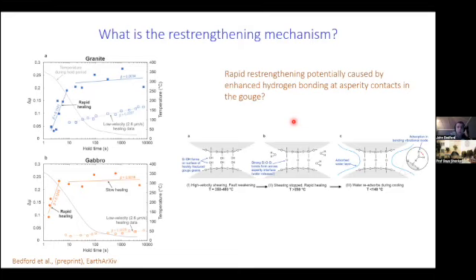And there's been quite a lot of work in the theoretical field of atomic simulations that show that when you shear silicate minerals and produce fresh fracture surfaces on them, the silicate minerals are very susceptible to form silanol bonds, which are SiOH material on the fracture surface. And these silanol bonds can then produce hydrogen bonding between cross-asperity interfaces once the gouge stops being sheared, or potentially it can also react to form strong siloxane bonds, which is Si-O-Si